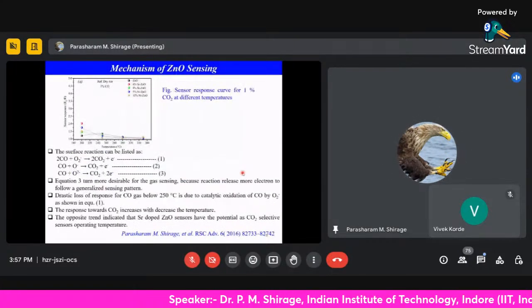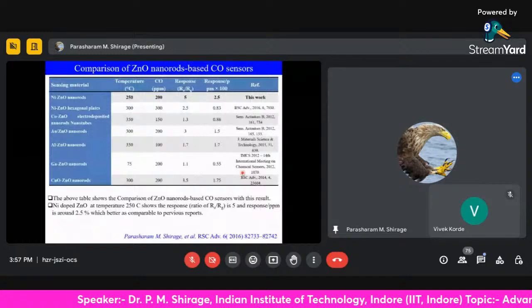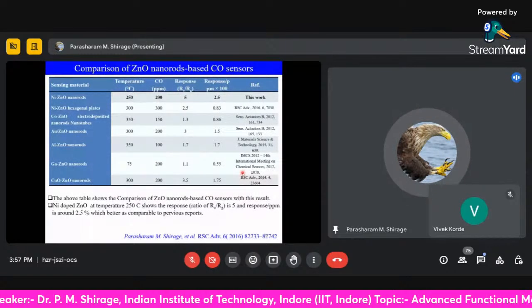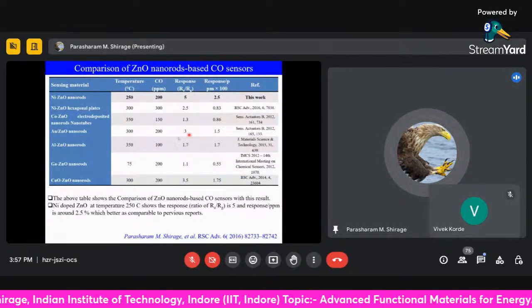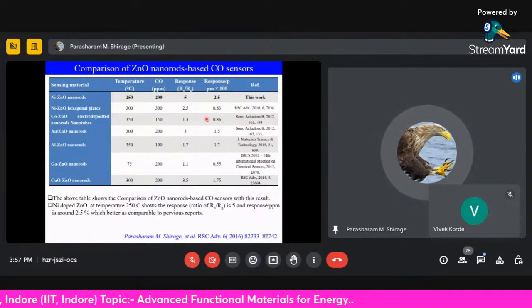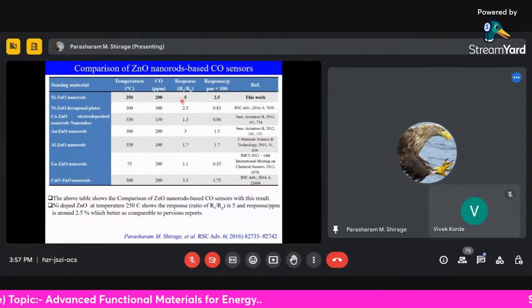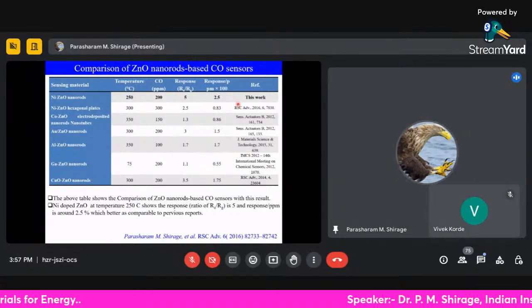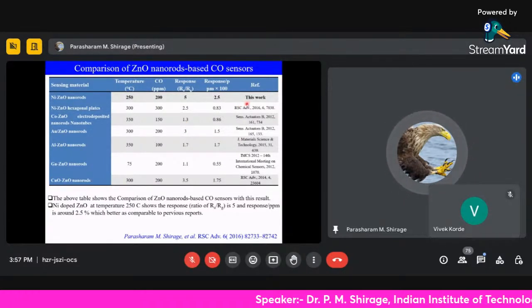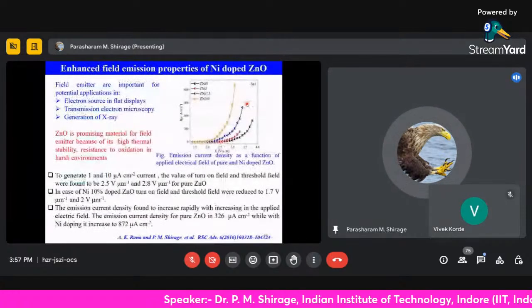Okay, so another important property is that our sensor works at about 250 degrees centigrade. Other sensors work at about 300 degrees centigrade. Okay, and our response and recovery times are very small, 5 seconds, and their capacity is also very good. Okay, so this is our interesting work.